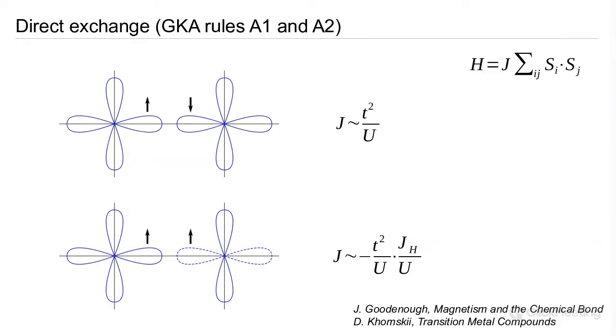So if we just define the exchange interaction, the Hamiltonian in the top right here, where H is J times the sum over Si dot Sj, essentially J here is an exchange parameter. Si and Sj are the spins on nearest neighbor sites i and j. So if J is positive, then this energy will be minimized for anti-parallel spins. So J is considered to be an antiferromagnetic interaction. And if J is negative, then this energy will be minimized for aligned spins, and J is then considered to be a ferromagnetic interaction.